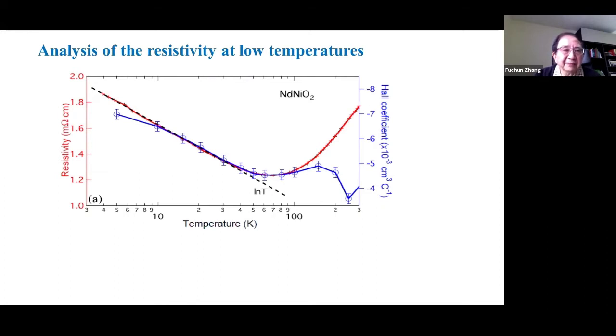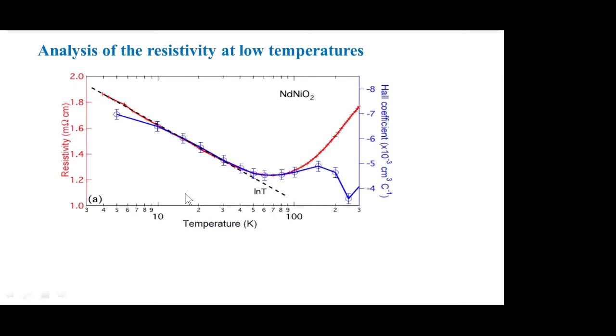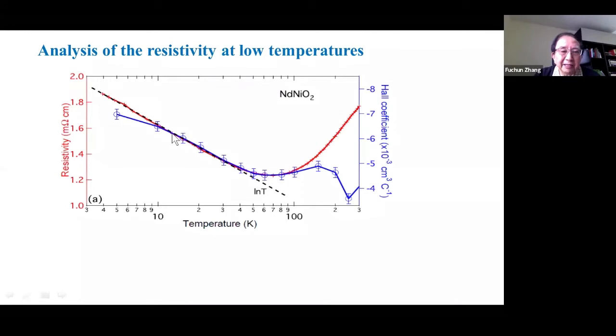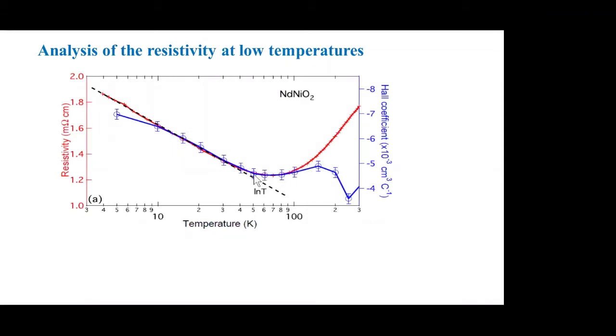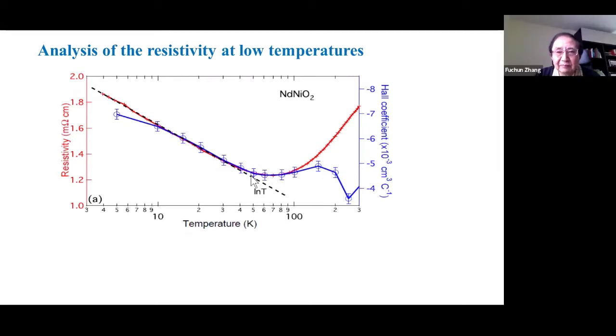Now I'd like to emphasize the resistivity at lower temperature. What I'd like you to see is that the red one is resistivity versus temperature, and the dashed line here is log T. At low temperature, from around 50 Kelvin, you can see the experimental data can be fit very well by log T behavior. That is a strong indication, suggesting this resistivity upturn is due to the Kondo effect, because in the Kondo effect, the conducting electron will be scattered by magnetic impurity, which causes additional resistivity.